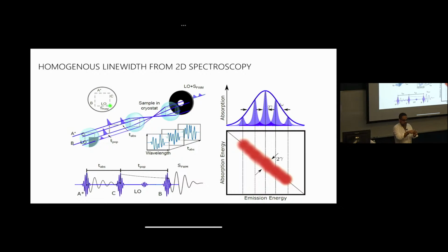You mix it with another replica pulse, you interfere it in your detector, and you have a way of measuring the amplitude and phase of this coherent response of the sample. So you measure a signal that is proportional to the third order susceptibility. It's a nonlinear experiment, and that has a lot of information on the optical structure of the sample. So you detect here the amplitude and phase of that coherent emission.